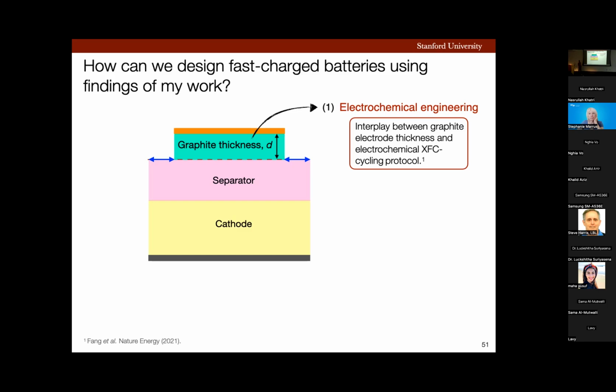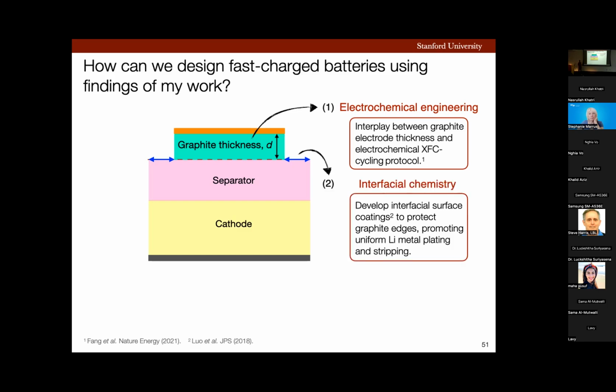Second, my work has shown that the area around the edges of the graphite is most prone to lithium plating. So can we use tools from interfacial chemistry to develop lithophilic coatings that promote or facilitate uniform lithium plating and deposition?